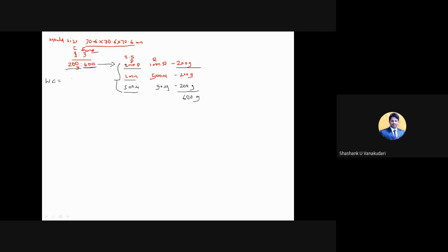The water quantity you can find out by using the formula (P/4 + 3), where P is in terms of percentage, and then the quantities of cement as well as sand, that is the total quantity you are going to consider: 200 grams of cement plus 600 grams of sand.